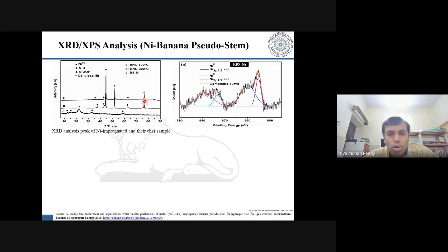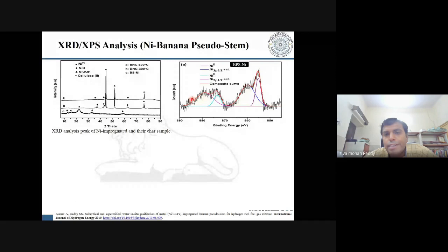Okay. Now, to further confirm the oxidation state of these metals that are formed during the impregnation and during the treatment, that is thermal degradation, we have performed X-ray photoelectron spectroscopy, where we found that the nickel is mostly present in the +2 form. So this is the composite red curve that we are going to see. This has been deconvoluted, and we see the pink peak, which corresponds to binding energies of 855 and 870, 880,